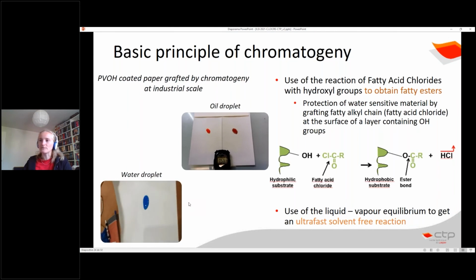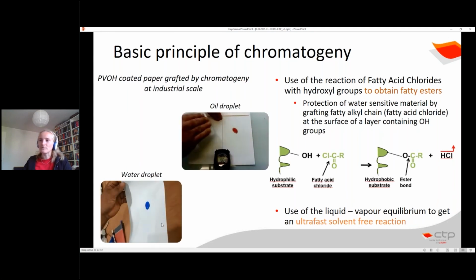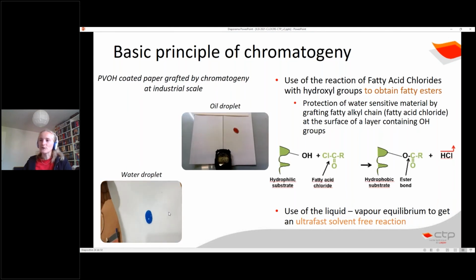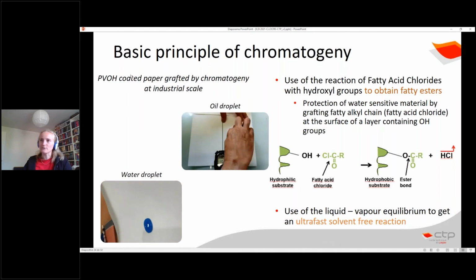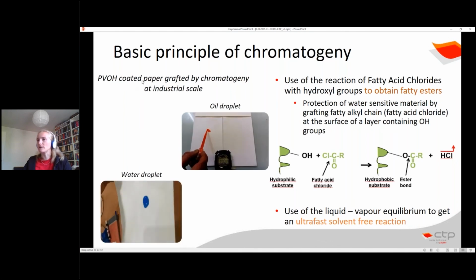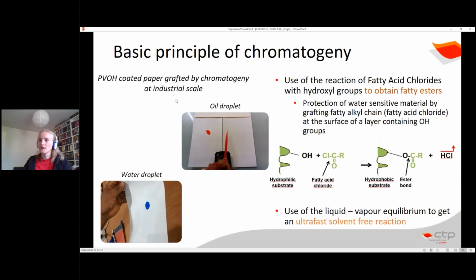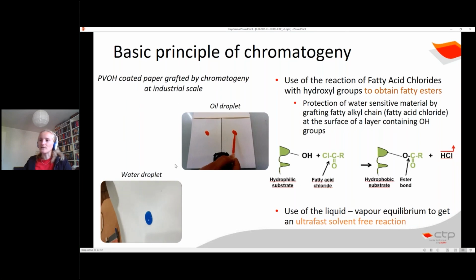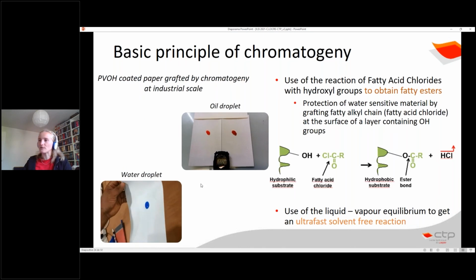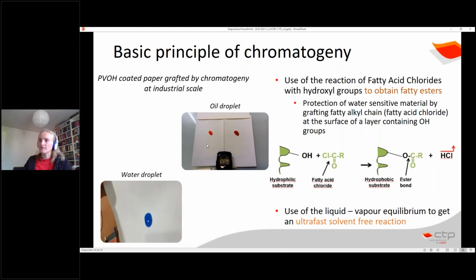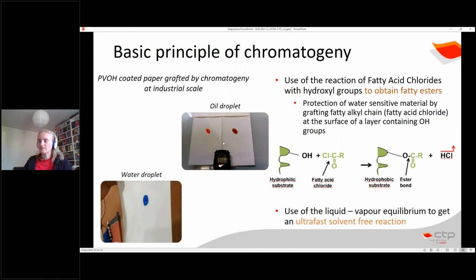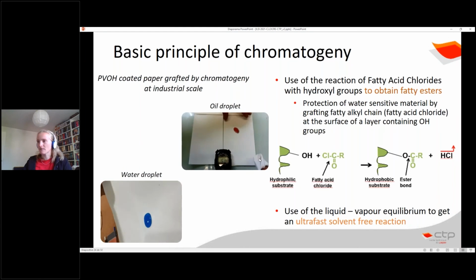So as you can see here on these two examples, this is a paper that's been treated using chromatogeny. That's been first coated with polyvinyl alcohol and then grafted using chromatogeny. And we see that it is perfectly hydrophobic. So the water rolls on the surface of the material without wetting it, and the oil here, it keeps the barrier to grease, and the oil does not penetrate into the substrate.